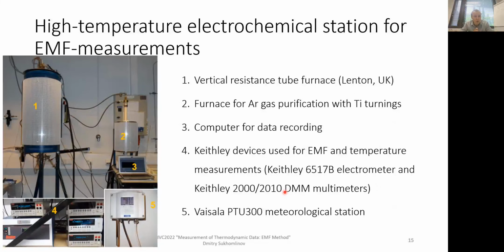That's how one of our experimental setups, the EMF station, looked like. Number 1 is the furnace. It's a resistance furnace with silicon carbide heating elements, a mullite work tube, and the galvanic cell is placed inside, right in the hot zone. And with 2 thermocouples inserted from both sides, top and bottom, the position of the galvanic cell was chosen in such a way that temperature gradients are at minimum, sub 1 degree, in pretty much all cases.